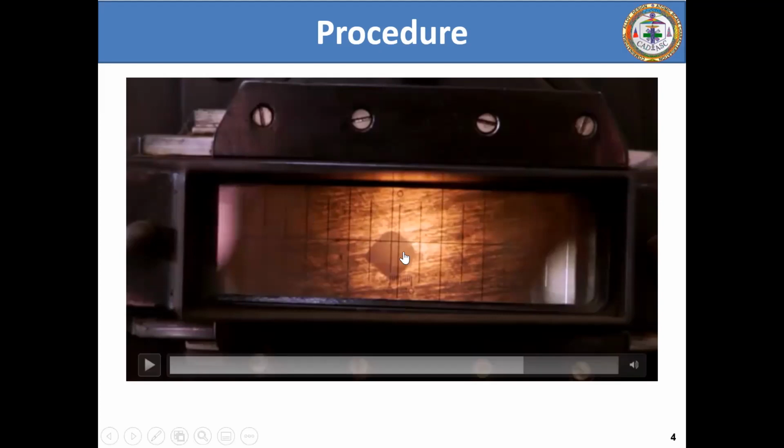But now there is another case also. Suppose the sides don't get rounded up, I mean there is no wearing of the sides. Rather, the wear and tear happens on one side of the indent, instead of on the corner. In this case, you will have a Vickers micro indent with a curved morphology. It will not be a square.